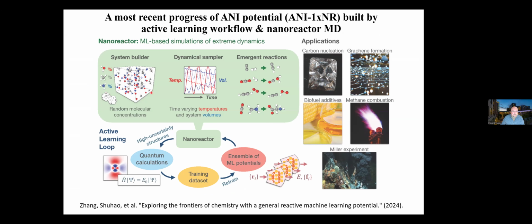What we did essentially was stuck small organic molecules into a small periodic box and induce high temperature molecular dynamics simulation, dynamically varying temperature and the volume. So essentially, you cook molecules and induce reactions, and you look for uncertainties and stop dynamics, run QM calculation, update your neural network, and again, details are in this reference. But what it allows us essentially to do is to make this reactive potential transferable to multiple different phenomena.